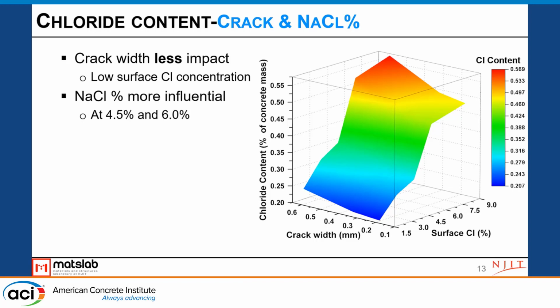And also, if we look at a specific crack width, the chloride content increases fast at 4.5 and 6% surface conditions. The chloride concentration is more influential at these two concentrations compared to the others.